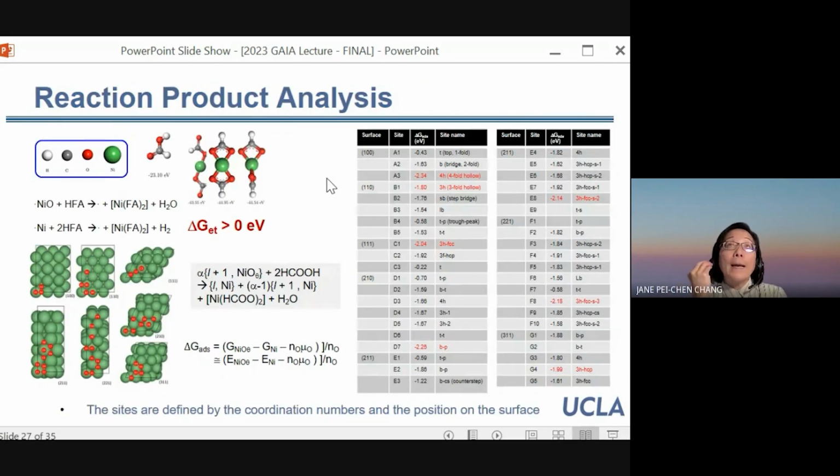And to design the chemistry that will allow us to pattern the material well, we typically will use some first principle calculations to help us identify the potential reaction pathway. In this particular case, I'm going to use nickel, which is one of the components in these multiferroic material systems. If we wanted to study the reaction pathway, we look at different surfaces, we look at different coordination numbers centering around the nickel that we're interested in.